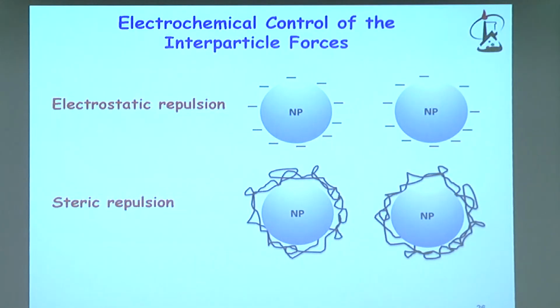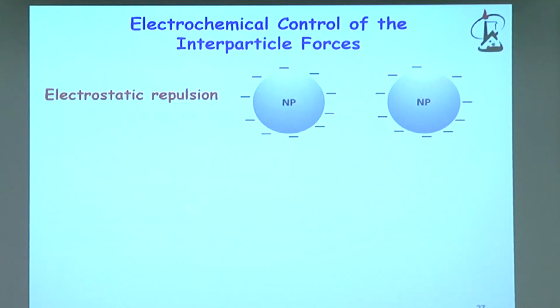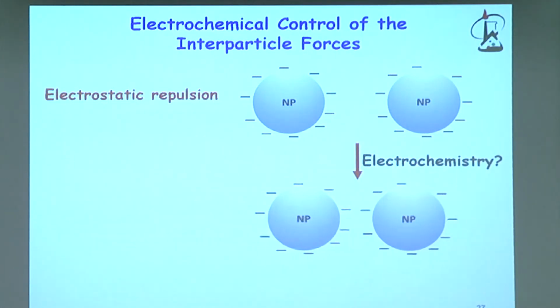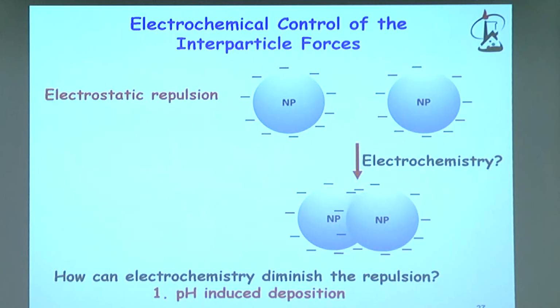And there are two ways to do that. One way is an electrostatic repulsion, which stabilizes them because they have the same charge, which means that they repel each other. The other one is steric repulsion. Everybody who works with gold nanoparticles in organic solutions knows that you can stabilize them simply by adsorbing a thiol, a long chain thiol, which physically prevents their spontaneous aggregation. So now the question, or the challenge, is how can you diminish, how can you lower this repulsion by applying potential? And one way to do that is, again, by changing the pH, which will change the charge of these nanoparticles. Again, one or two examples.